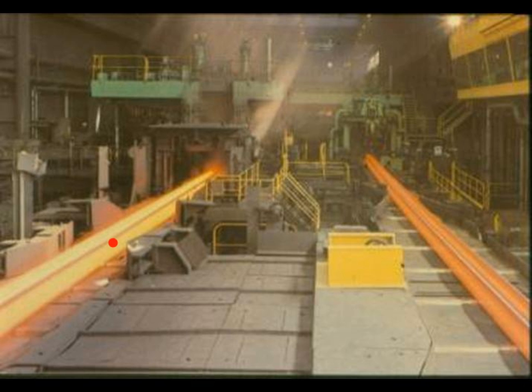For the strand on the right, you can see the tips are cooled even further, but I'd like you to notice in particular the web to flange region, and even the color here is showing us that we have a little bit more heat at that center region. Now that has to do with the cooling rate that's experienced in that region.